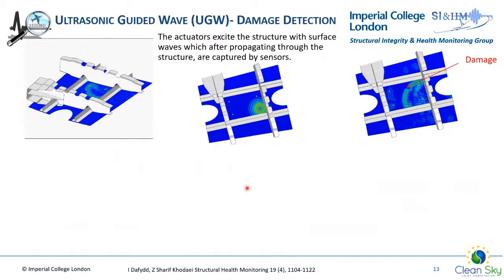Guided waves, as you can see in this video here, are waves that are generated in thin plates, and they travel guided by the upper and lower surfaces of the plate structures. They travel long distances, but of course they have different characteristics. They are dispersive, and the velocity depends on the frequency and the thickness of the plate. The propagation property depends on the material properties that they travel through. So the idea is that when these waves are traveling through the structure, if there is damage present, the characteristic of the propagation changes.